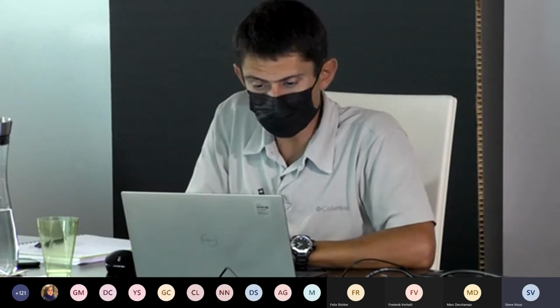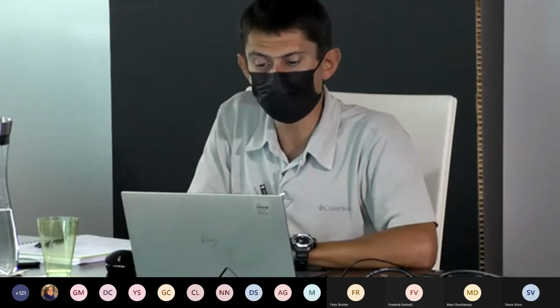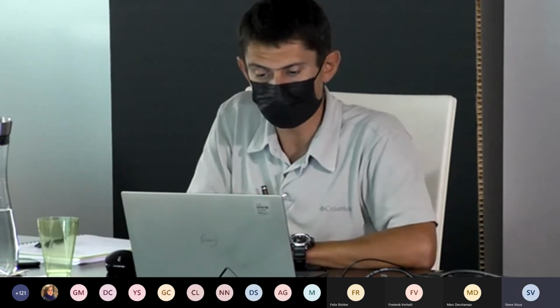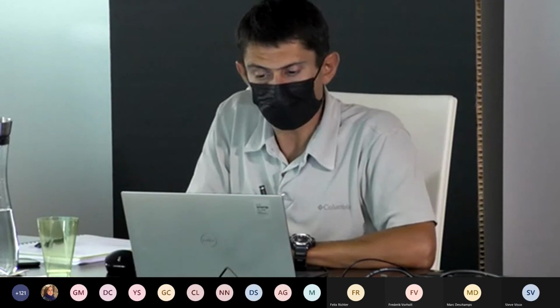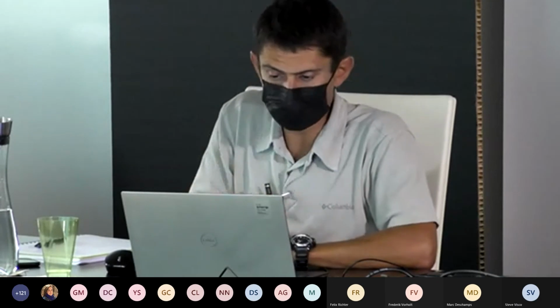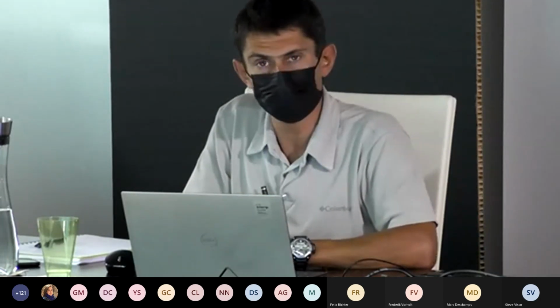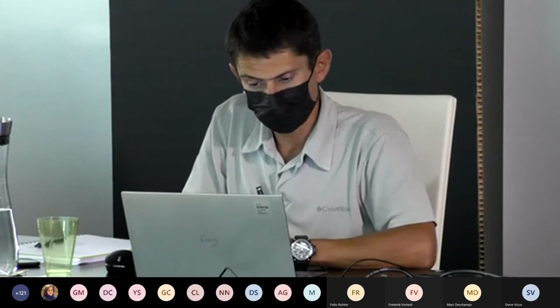Thank you very much, Stephen. And in this kind of glassy materials, the shear modulus of this layer is strong enough to block the growing of lithium dendrites. That's correct.